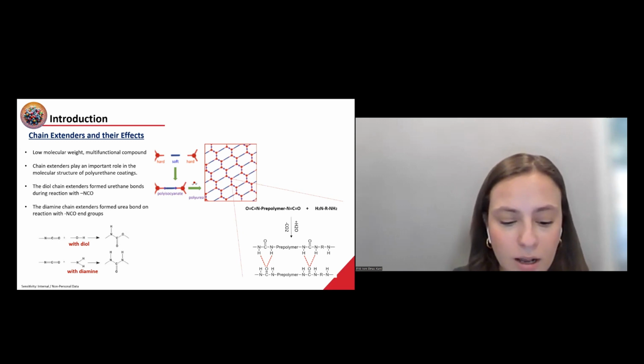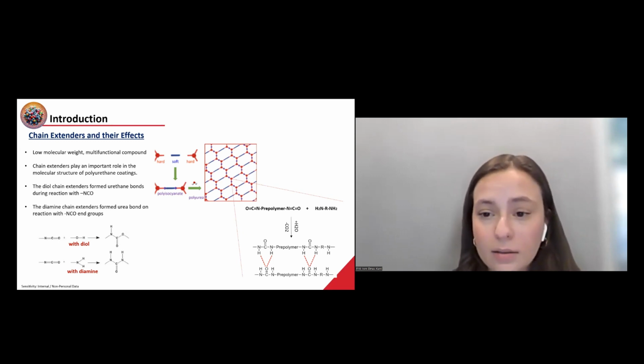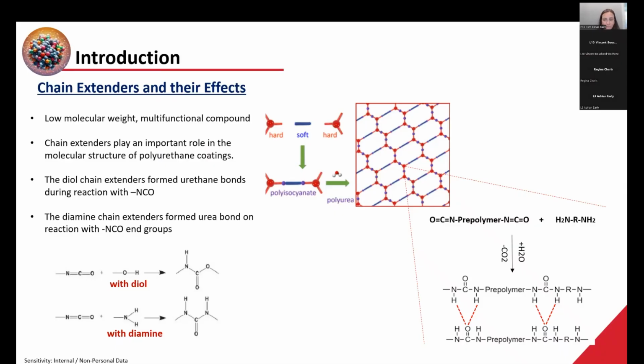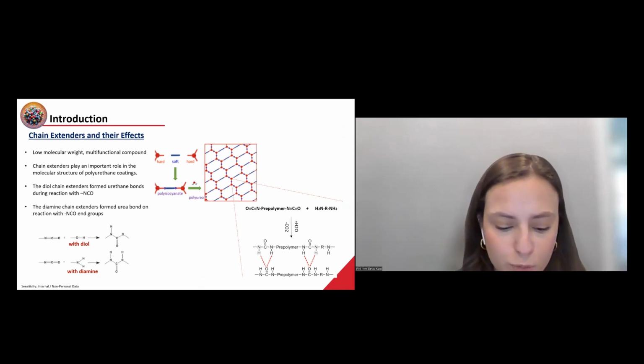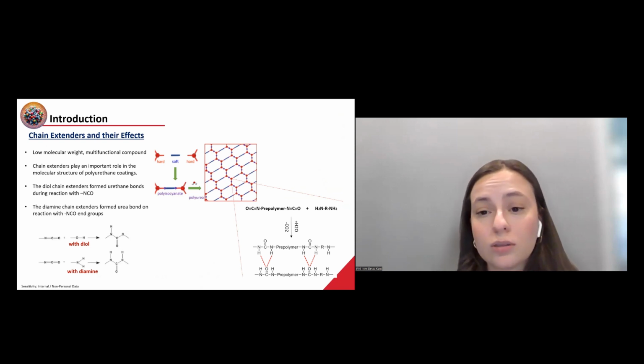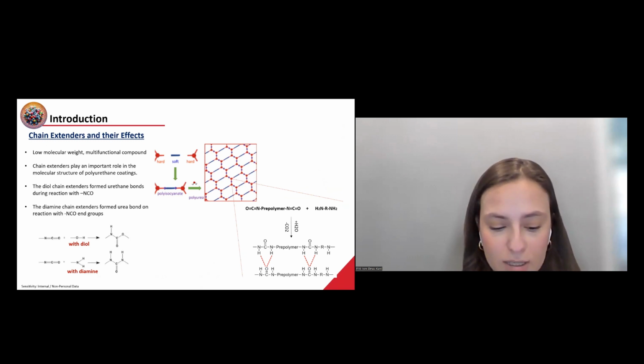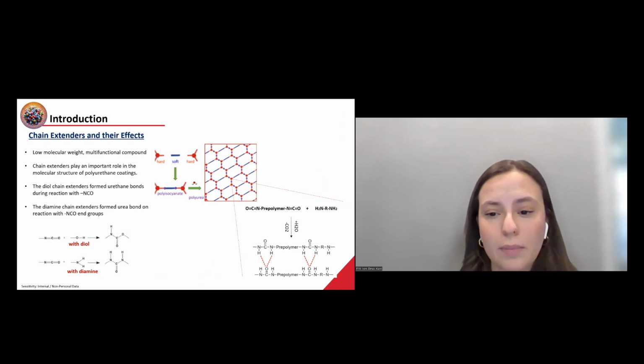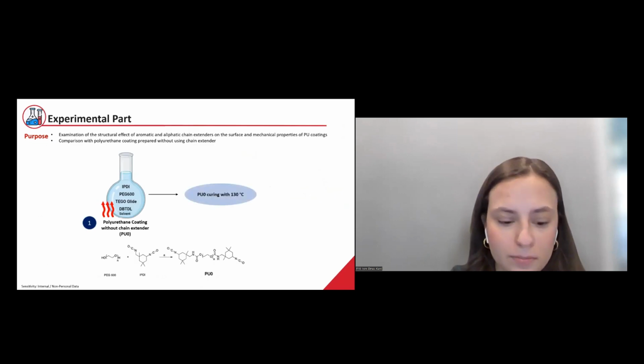The isocyanate groups in the polyurethane-urea structure are highly reactive and can undergo a reaction with moisture present in air. And the moisture reacts with the isocyanate group to form urea linkages. And this process leads to the cross-linking of the polymer chains and formation of a three-dimensional network structure.